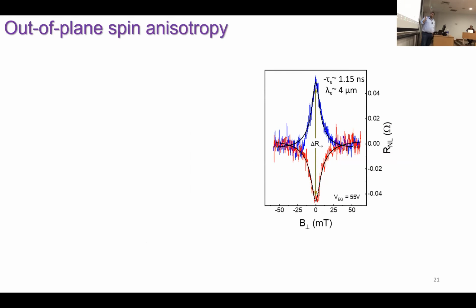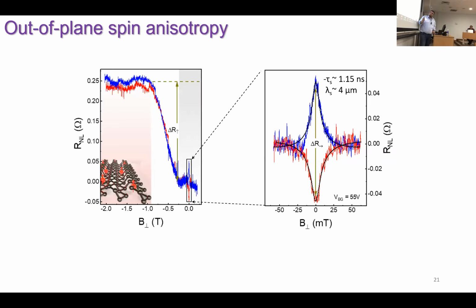And we started to do also some out-of-plane spin anisotropy measurements. So these are the typical Hanle measurements that I show. If you would measure this sample with the graphene, this high field range that you will see would have the same amplitude. But in the case of the black phosphorus, the signal is almost 5 times more than what you would get with the in-plane spin current, which is already indicating a very strong spin anisotropy in this material.